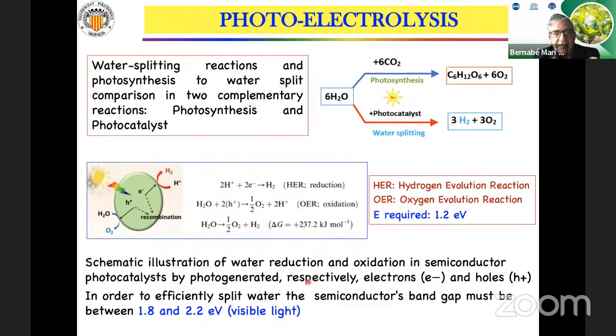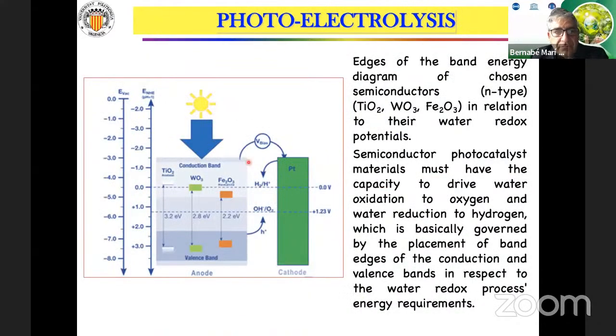Right now, these techniques start to be operative using titanium oxide, but the titanium oxide band gap is very large. It is better if you are able to use visible light, so you use the sun spectrum more efficiently, and between 1.8 and 2.2 electron volts is enough to produce the splitting of water. We need materials to do that. In the beginning, people started to work with titanium oxide, but the gap is 3.2, so this material only uses the UV part of the sun spectrum.